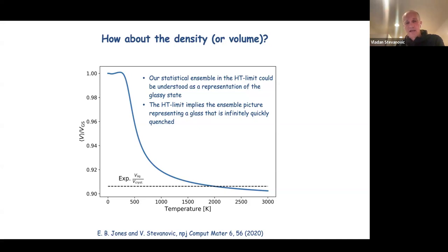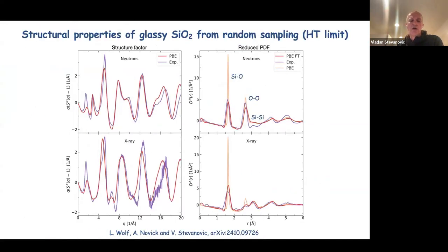And in order to test that hypothesis, I will just show you the results on an actual glass. Silicon is kind of amorphous. It doesn't exactly undergo a glass transition. So this is our very recent result on the structural properties of SiO2 that we modeled using, again, a large collection, 3,000 in this case, of 24 atom cells.